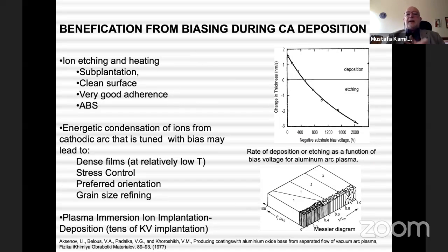So how do we benefit from biasing during cathodic arc deposition? Generally, when you start to do cathodic arc deposition, you start with an application of high voltage bias. This high voltage bias results in etching and heating of our substrate material. So in this case, we get a very clean surface, we get some implantation, and this is one of the main reasons why we have a very good adherence of the cathodic arc deposited coatings.